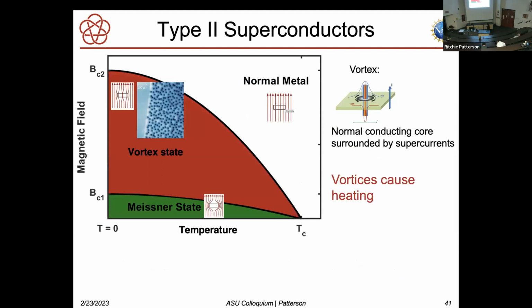So just as a reminder of the phase diagram, here's the temperature of a type 2 superconductor, and we're talking typically about niobium, versus the magnetic field. Down at very low magnetic fields, you're in the Meissner state where you exclude magnetic fields from the interior of the metal. At higher magnetic fields or higher temperatures, of course, the magnetic field goes in the metal. In between, you have this vortex state. A vortex is just a normal conducting core surrounded by supercurrents.